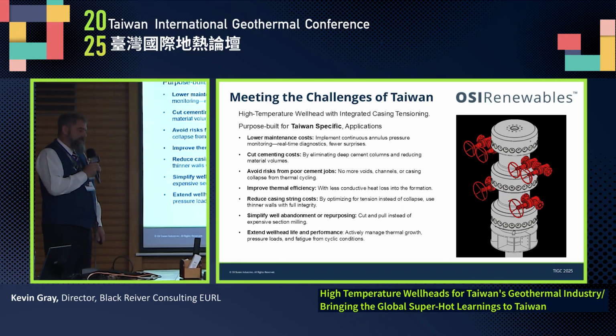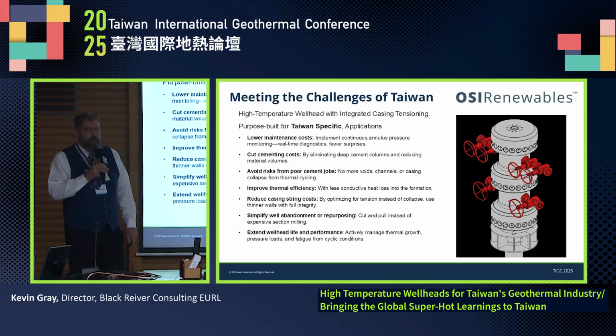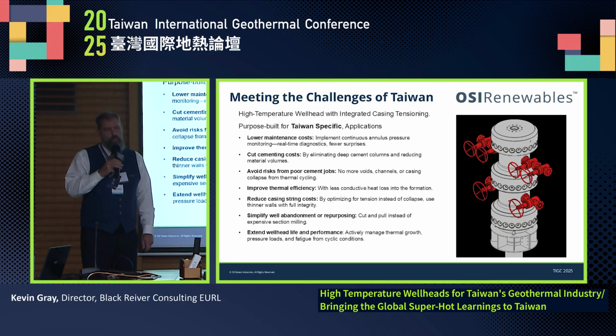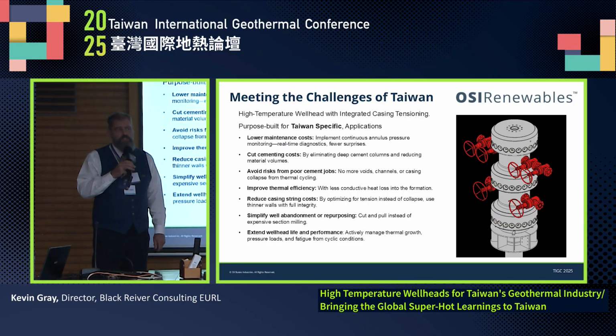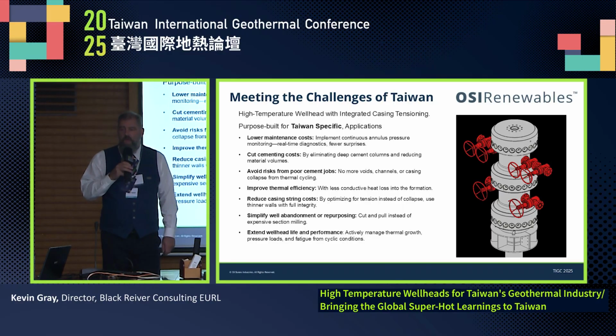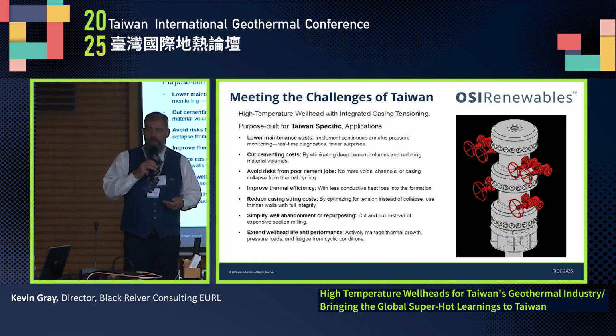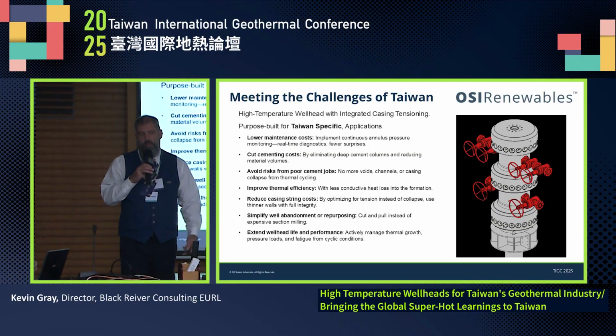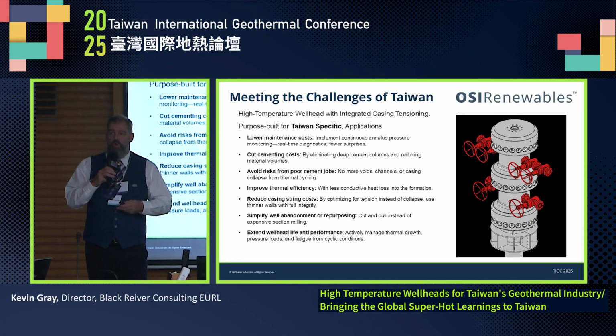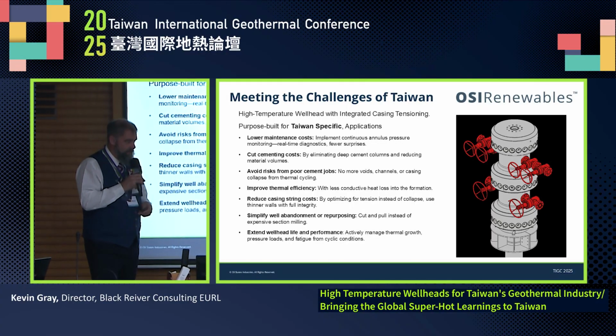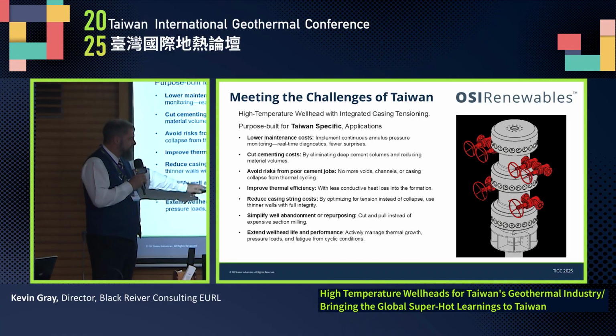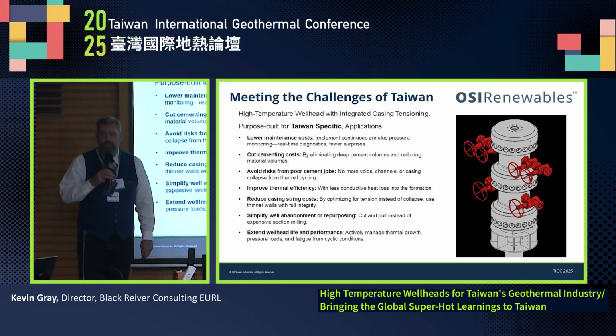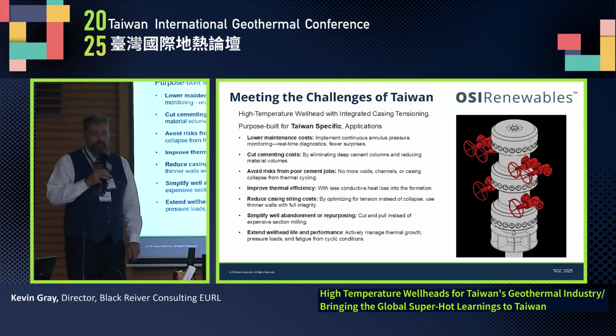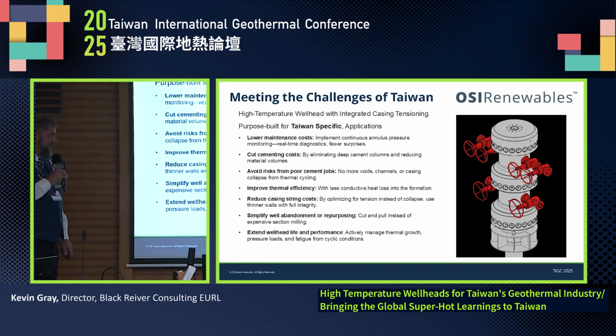The other thing that is quite useful, when we do our life carbon footprint analysis of our geothermal well, we've got to include the casing steel as being used up and lost in the hole. With this system, because we're not cementing all the way back to surface, we can do a traditional oil field cut and pull operation on our casing string. So we can go into the well just above the cemented section, cut the casing and recover the rest of the steel to surface, at which point that's discounted from our carbon footprint. The other thing that we have is we can actively manage the thermal growth, and we can reduce the amount of wellhead fatigue that we get from the expansion and contraction of the casing string.